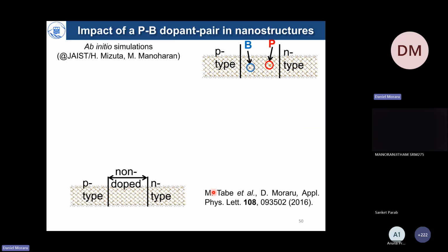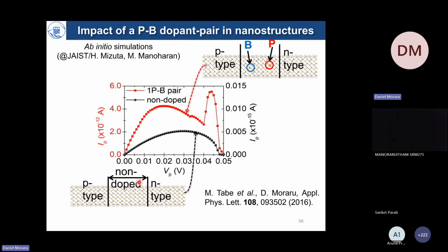Now, that was not enough for us, and we wanted to understand the physics more, and we appealed to ab initio simulations where we mimicked our nanowires as p-type, n-type wires with exactly one phosphorus and boron on each side and compared them to the non-doped case. And under the right conditions, we can indeed observe this kind of sharply enhanced current peak, which only belongs to the case when a phosphorus and a boron dopant mediate transport from one side to the other. What this means is that we are looking here at an atomic-level p-n tunnel diode.